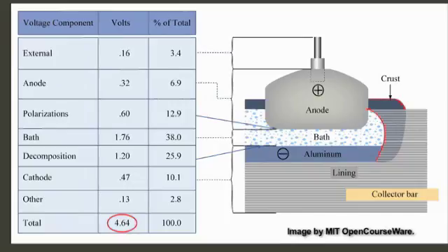So you can see this is like a drafting pencil. It's constantly being fed. And to give you a sense of scale, this is probably about 10 feet across. And this gap is about 2 inches. And this is about 1.5 feet deep, sitting at about 1,000 degrees centigrade. Liquid aluminum and liquid salt.